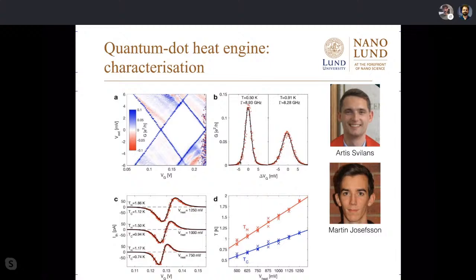So to show you how well this matches, these are conductance peaks. On the left hand, you have what we call a stability diagram. So basically we measure conductance through the quantum dot as a function of two voltages, an external bias voltage that we can control and a gate voltage that basically sets where our chemical potential is relative to the conducting states of the quantum dot. And if you look at zero bias voltage across here, then you cross points where the quantum dot conducts. And a cross section through here would be such a graph of this. So the black line is, sorry, the black line is theory and the red dots are experiment. And you can see that this fits very well.